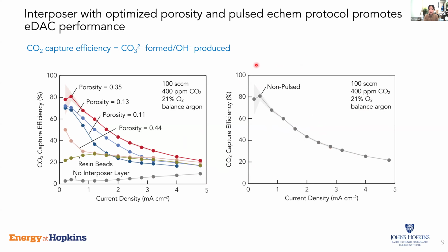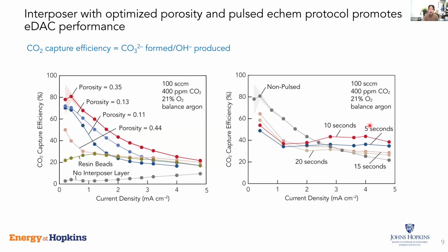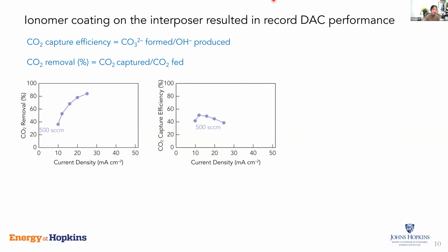So without pulsing, this is our typical performance. And as we do some pulsing protocols, so this is 10 seconds on and 10 seconds off, we can see that our high current performance, the efficiency is a lot better at high current. So then we decided to use the best porosity resin wafer and then the pulse current to demonstrate our performance. So this is at 500 sccm CO2 air inlet flow rate and at different current density. So in addition to capture efficiency, we also care about how much CO2 is being removed from our inlet gas, right? So as you can see, we increase the current density, we can achieve about 80% of removal of CO2.